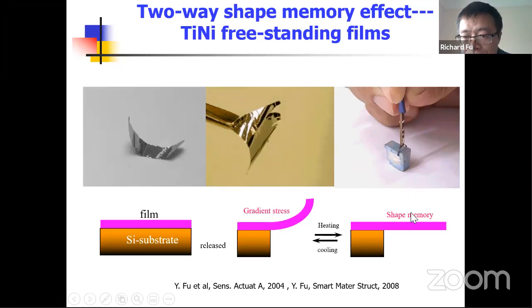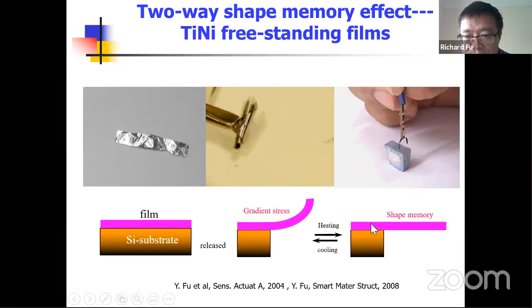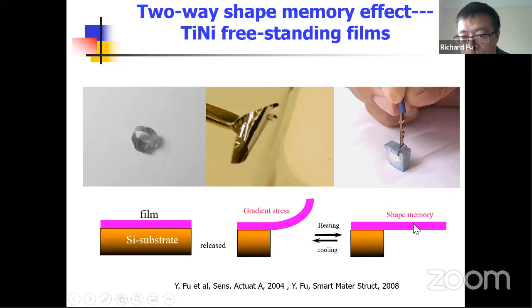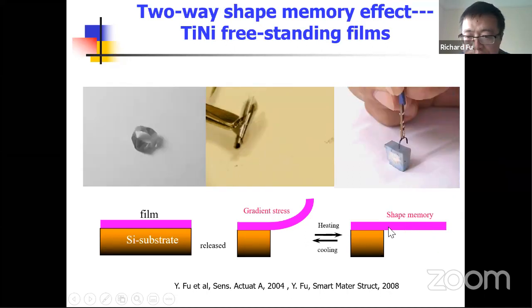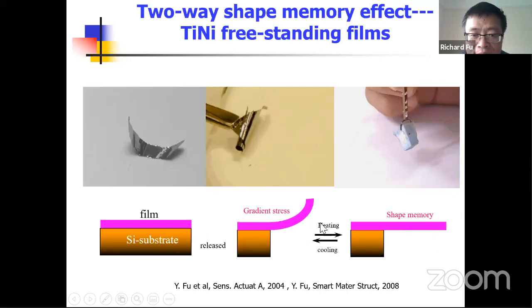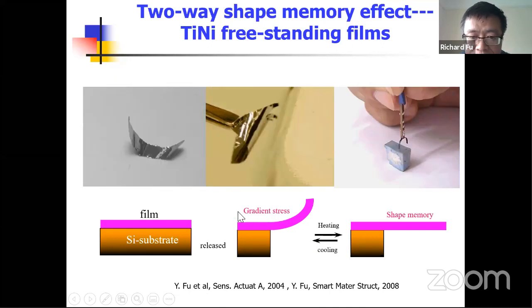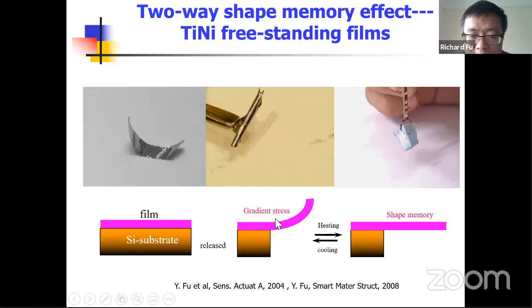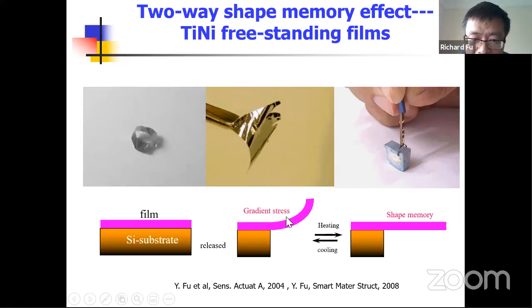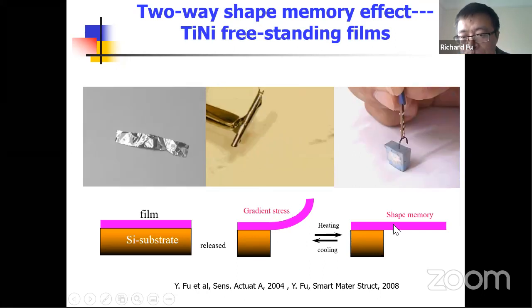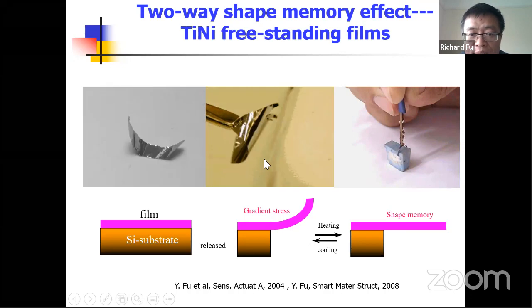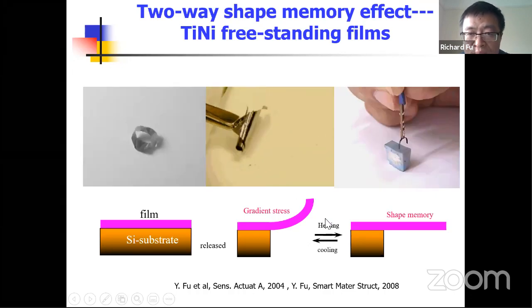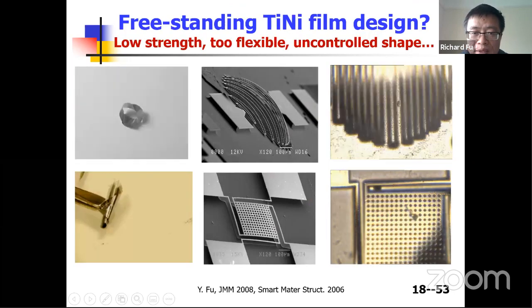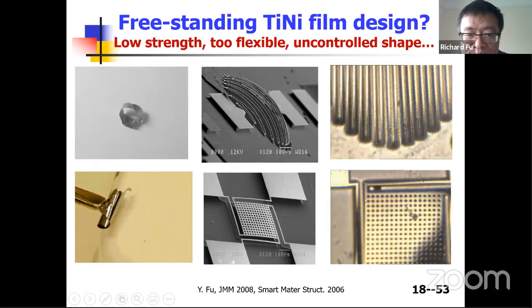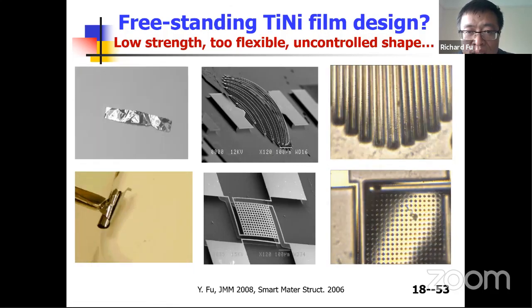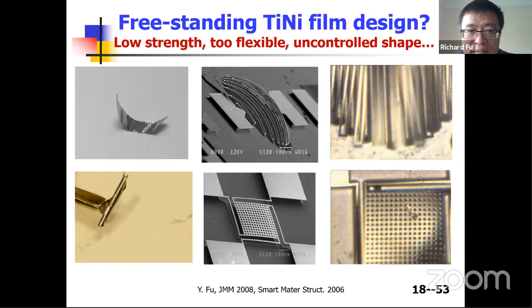So the film will curl up after you release it from the substrate. If you heat it up, there will be a shape memory effect, which causes the shape to return to the high temperature deposition shape, which is flat. So that means the material itself, after deposition, has a two-way shape memory effect. Once it's cooling down, it curls up. Heat up, it becomes flat. So you can use this as an actuator itself. We can use lithography methods to design different structures to realize the microactuator design.